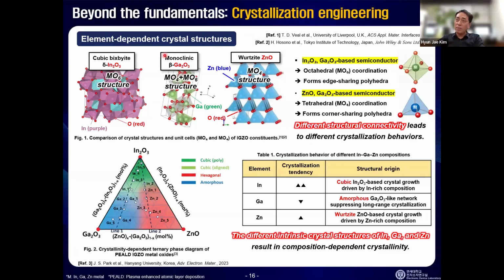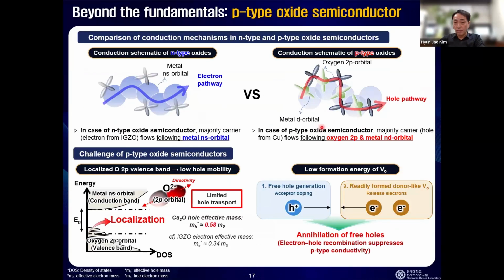Okay. And now this is a recent trend. As deposited, it is usually amorphous, right? But they try to crystallize. But indium, gallium, zinc have different crystal structures, different coordination numbers. So they try to manipulate, sometimes, because they have different crystallization temperatures. Okay, so indium, one more time, is easy to crystallize. And gallium is difficult to crystallize. Okay, and not only this material, there are other materials they try to use. This is one example. This is the recent trend, crystallization of this oxide semiconductor.